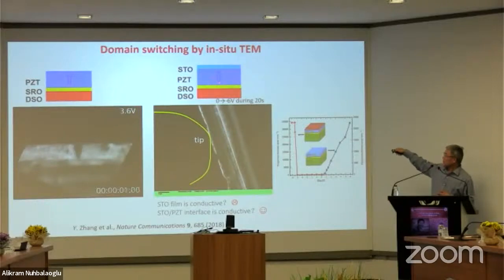And this is another sample, very similar to the first one. You have an insulator, a two-dimensional conducting oxide as the bottom electrode, this is the ferroelectric, and this is another insulator. So this structure is similar to that, except for an additional thin STO. Then you apply an electric field on top of the STO across this PZT, and you see the important things happen.